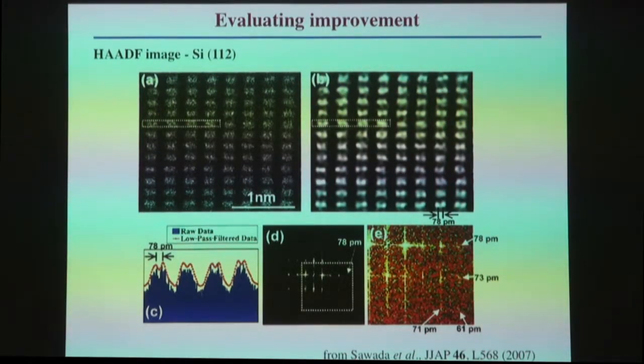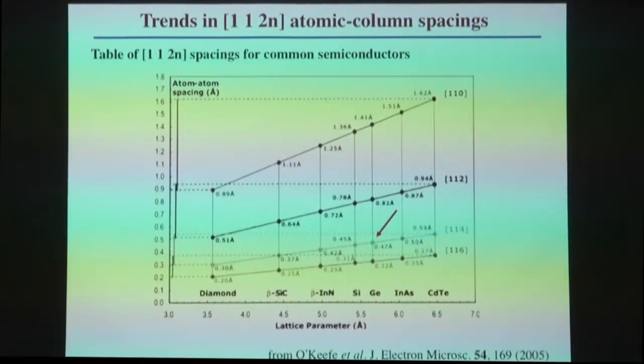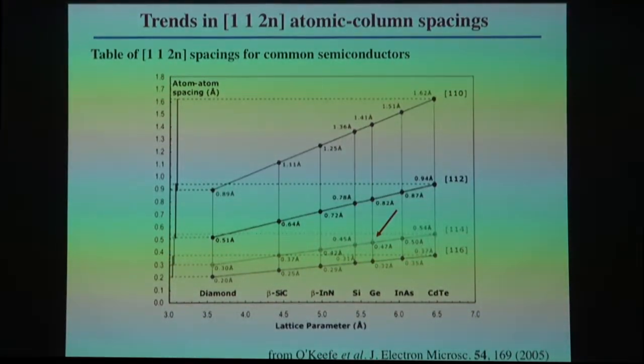And so here is just an evaluation these days. This is the resolution test for all new aberration-corrected microscopes. Silicon 112. Here is silicon 112. A little bit of filtering involved here. You do a low-pass filter, and yes, it's a bit noisy, but you can say, okay, I can resolve the silicon dumbbells in 112 projection in this particular case. And what O'Keefe showed was that amongst all of the elemental and compound semiconductors, you could start off in the 110 with cadmium telluride. You could go to indium arsenide, germanium, silicon, all the way down to diamond.